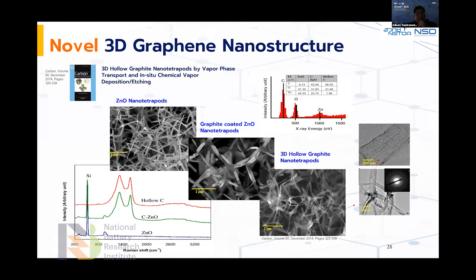And also another research work that we first invented is how to use zinc oxide nano tetrapod as a template for making graphene aerogel. We use the zinc oxide nano tetrapod like this, and then we CVD grow the graphene on the surface of the zinc oxide tetrapod. Then we can etch away the zinc oxide and leave only 3D hollow graphene nano tetrapod. And it's really fluffy and really light material, and also has a really high surface area.